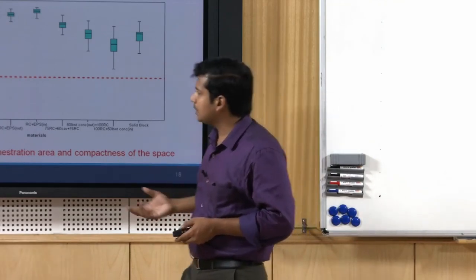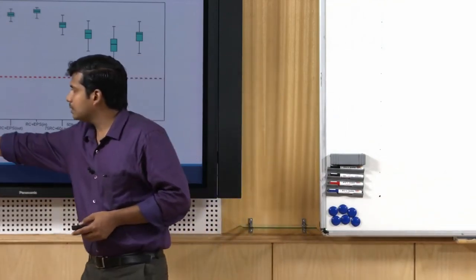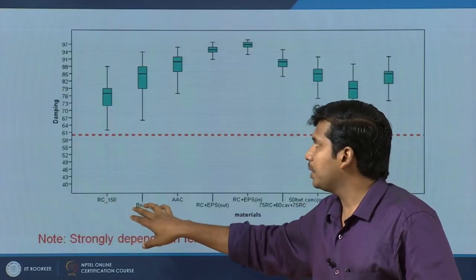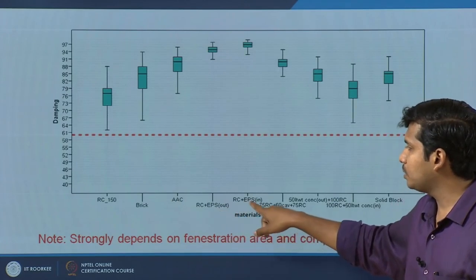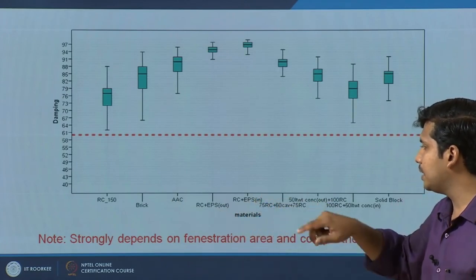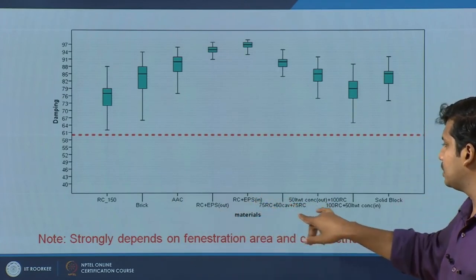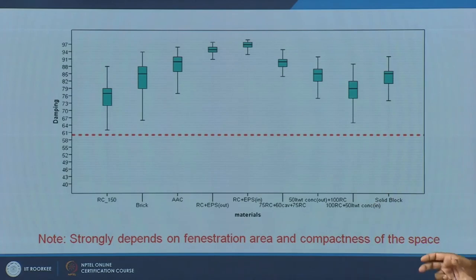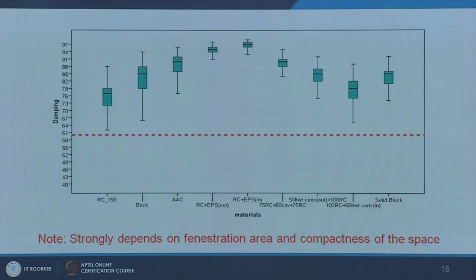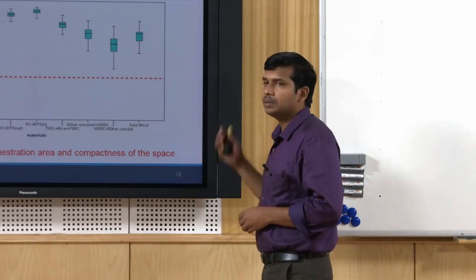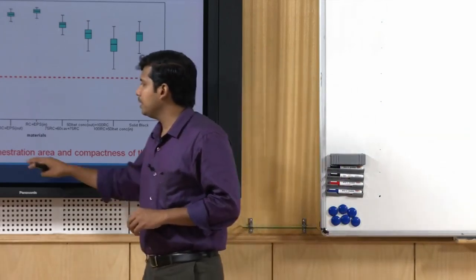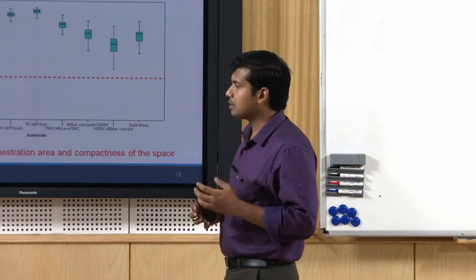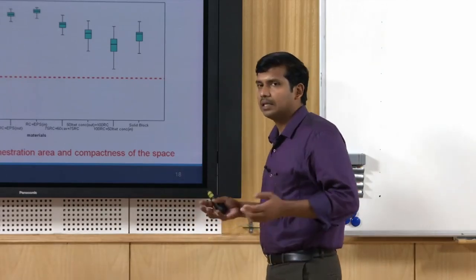Most of the materials tested — a 150 mm concrete wall, 150 mm brick wall, aerated concrete, insulated wall with outside versus inside insulation, cavity wall system, solid cement block system — most of them had thermal damping above the prescribed limit. However, it is critically dependent upon the fenestration area.